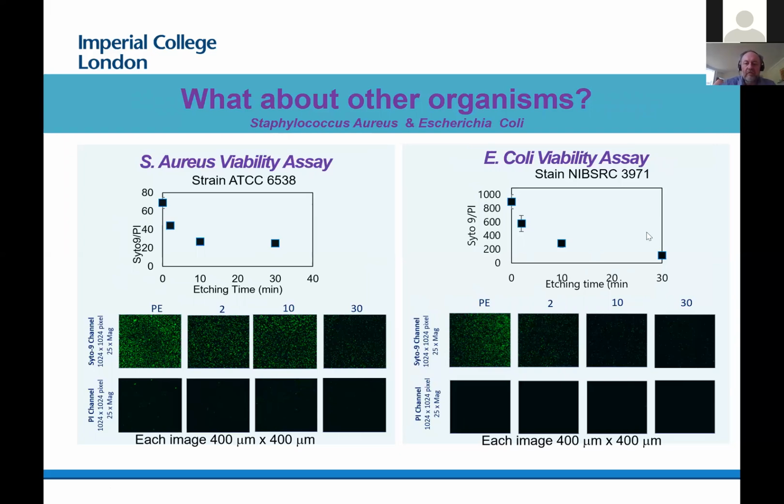And in the case of the E. coli, a reduction of maybe a factor of 50 to 60 in terms of the viability. That is the population of viable cells we can see on the surface. So the short conclusion from this section is that even for other bacteria that are quite common, these simple oxidation processes, changing the surface appearance of polymers, can certainly indicate some improved performance around antimicrobial behavior, which is encouraging.